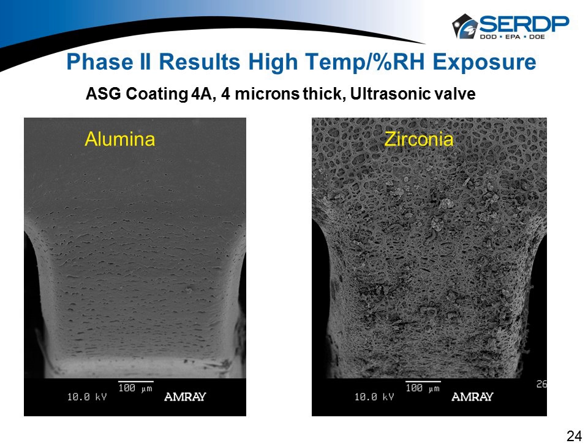One thing we found out right away, we were all kind of giggly. We thought, yeah, zirconia is just going to blow the socks off alumina, and it was a miserable failure. And when we got looking in the SEM, we found out why. You can see here on the left, this is alumina, and alumina has its nice 10 nanometer particles. Zirconia, while a different particle, they were again the 40 nanometers, and you can see whiskers growing all over this creature. And the coating does not go down nearly as smooth, and so it doesn't create a surface that seals off. So while we thought zirconia would have been an improvement, it wasn't. Alumina, again, as in phase one, outperformed.